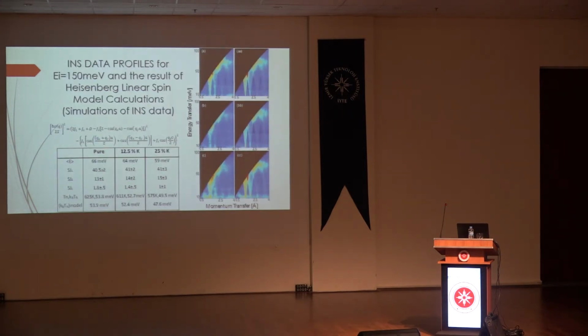Now, we got this thing, the energy equation over here. Then we start fitting the data. The fitting basically uses a Monte Carlo integration routine. We fit the Monte Carlo integration routine for the primary case for 5,000 Q, random Q values between 0.5 to 4. That means it is a powder scattering. So for each Q value, for each 2 theta value, other ways of saying, there is a sphere, and those spheres basically scatter on the detector. And we have in the preliminary 5,000.